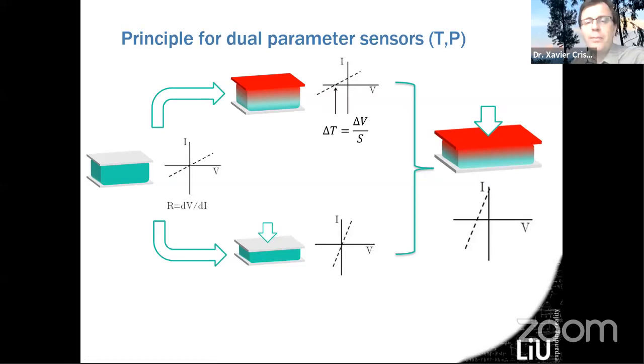So if you succeed to make a material where those two parameters can be read independently without crosstalk, then you get an interesting material. The goal is to have such a material that when you apply a pressure and at the same time a temperature gradient, the curve will be shifted by a certain value, and you can access temperature. The slope is connected to the pressure, so that you can read both at the same time. So this is the goal.